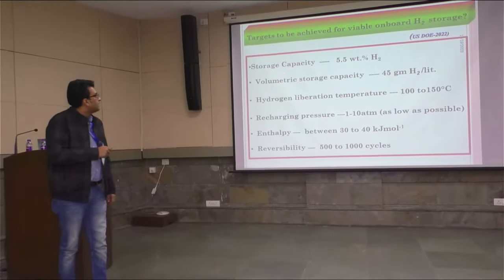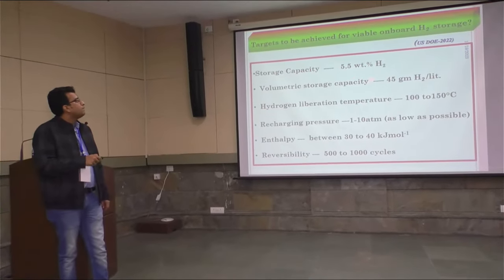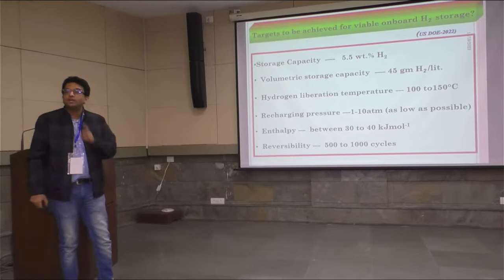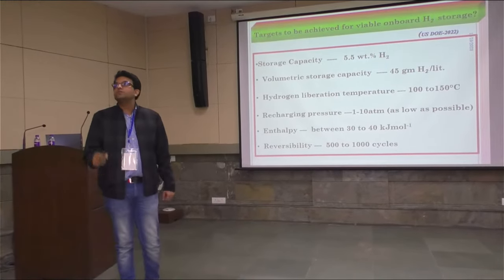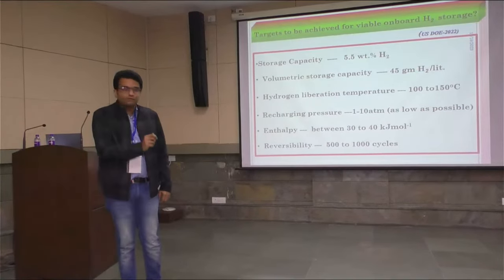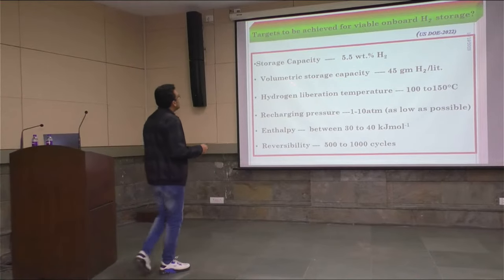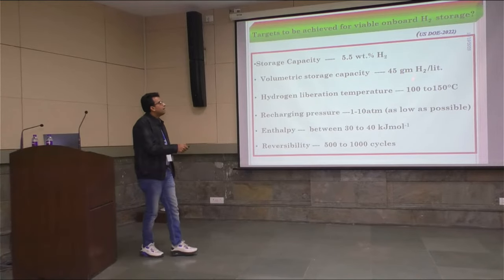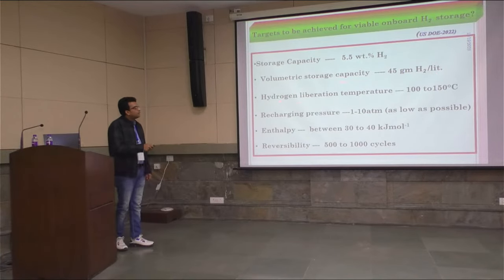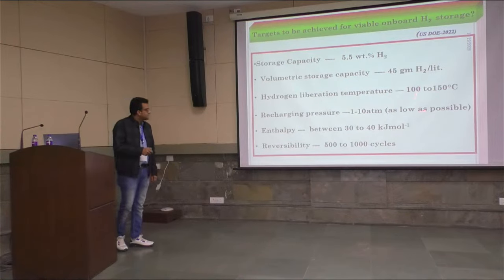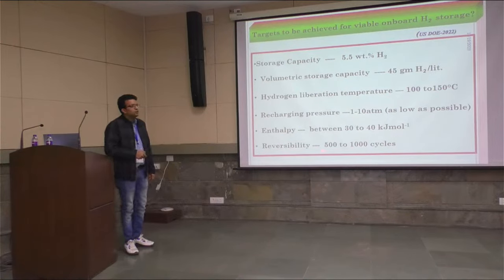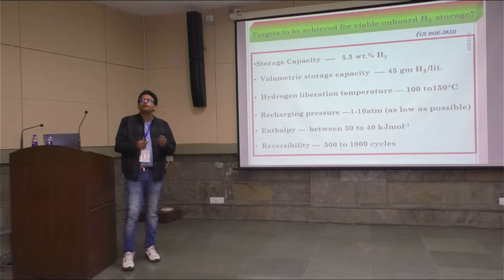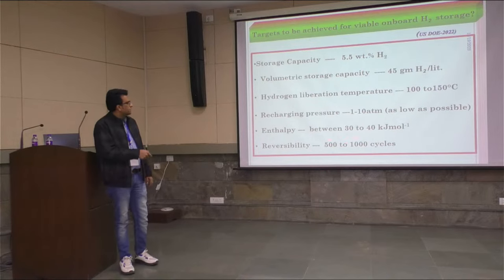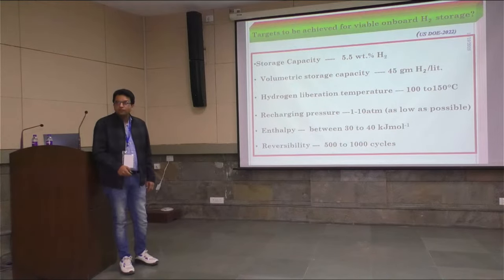And according to that target, a material should have 5.5% hydrogen storage capacity. That means 100 gram of material should store around 5.5 gram of hydrogen. It should have a volumetric storage capacity of 45 gram hydrogen per liter, a hydrogen dissociation and absorption temperature of 100 to 150 degrees Celsius, and it should be reversible, like charging a mobile, you can charge the hydrogen in this material within 500 to 1000 cycles.